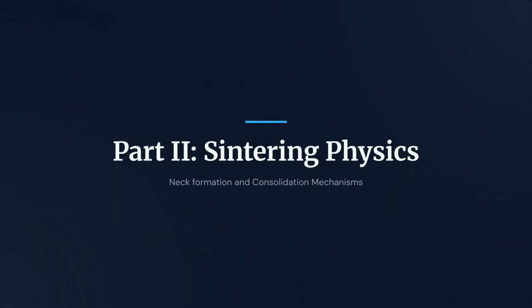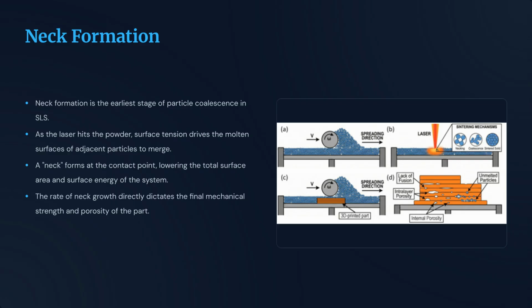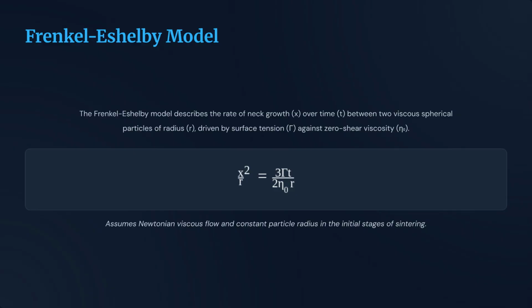Moving on to part 2, we will look at the physics of sintering, focusing specifically on neck formation and consolidation. Neck formation is the earliest stage of coalescence. As the laser hits the powder, surface tension drives the molten surfaces to merge, forming a neck that directly impacts the part's final strength. The Frenkel-Eshelby model mathematically describes the rate of this neck growth, assuming Newtonian viscous flow in the initial stages of the sintering process.